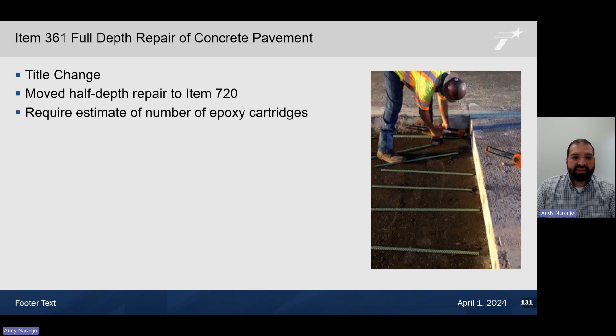Because of the issues we have with epoxy grouting anchors, we are now requiring the contractor to provide an estimate of the number of epoxy cartridges needed for each repair location. This will provide TxDOT a better estimate of whether the contractor is utilizing the right amount of epoxy in each hole. The picture shown is a repair operation where the contractor was not utilizing an adequate amount of epoxy — using very few cartridges per hole, resulting in inadequate anchoring of those rebars.